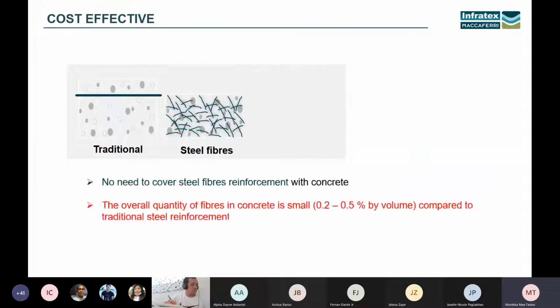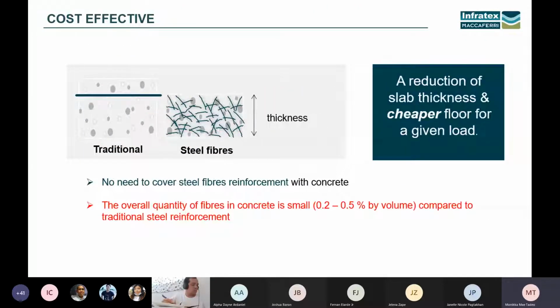Okay, so another one would be it is cost effective. From experience, conventional slabs with a thickness of 200 millimeters, we can reduce to 180 or even below. So there will be a reduction of slab thickness and a cheaper floor for a given load. Normally for traditional slabs, we have concrete cover, normally 40 millimeters. For steel fibers, we don't need to use it anymore, so we can reduce the slab thickness.